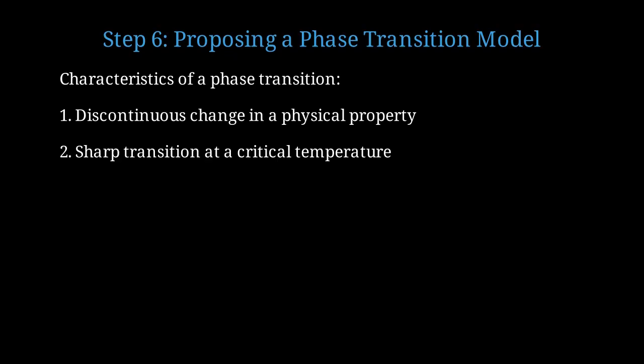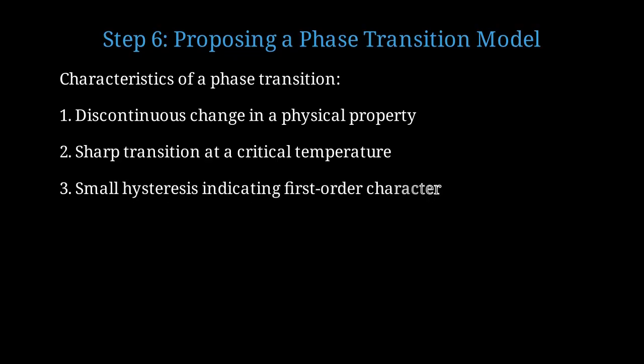Based on these observations, we can propose that superconductivity is a thermodynamic phase transition. Let's think about what this means. What are the characteristics we observe that suggest a phase transition? First, we have a discontinuous change in a physical property. The resistance drops abruptly to zero. Second, the transition occurs at a well-defined critical temperature that is reproducible and characteristic of the material. Third, the small hysteresis suggests first-order character, though we'll later learn that superconductivity is actually a second-order phase transition in zero magnetic field.